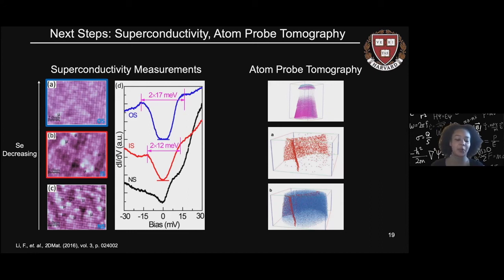Our next step was hopefully to grow a bulk of iron selenide on top of a bulk of strontium titanate and see if that increased the cohesive force and allowed us to produce a successful measurement that didn't result in our sample blowing up, but we didn't have time to employ that technique. So that's definitely a next step we want to try. And it's also a big question of why it was unsuccessful.